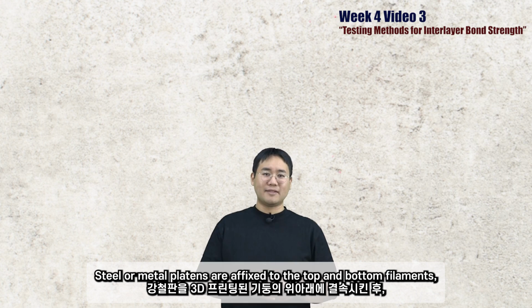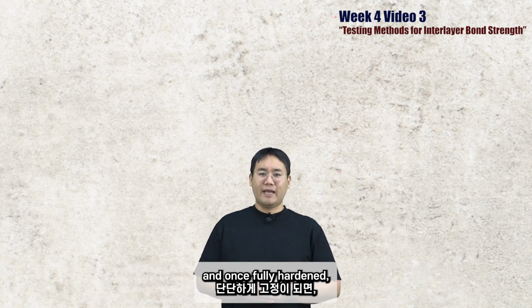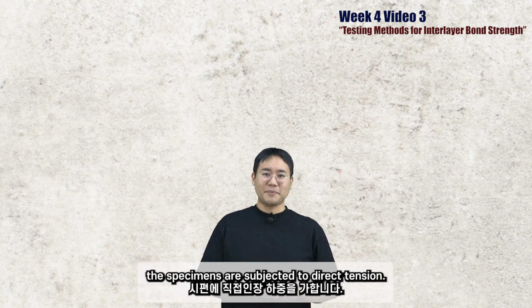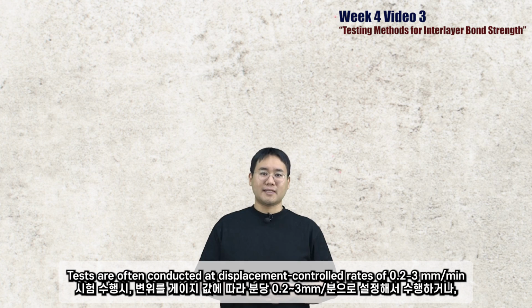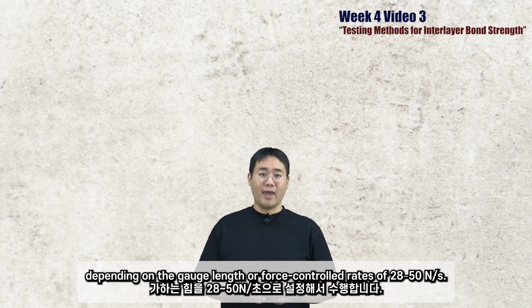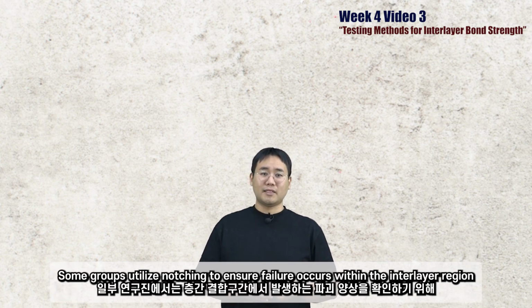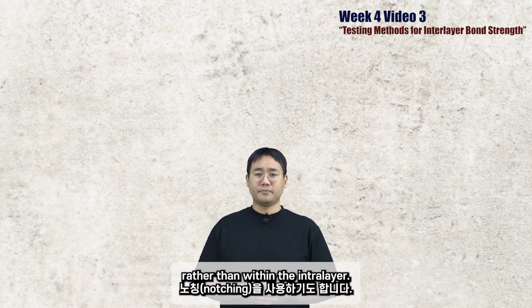Steel or metal plates are affixed to the top and bottom filaments, and once fully hardened, the specimens are subjected to direct tension. Tests are often conducted at a displacement-controlled rate of 0.2 to 3 mm per minute, depending on the gauge length, or a force-controlled rate of 28 to 50 Newton per second. Some groups utilize notching to ensure failure occurs within the interlayer region rather than within the intralayer.